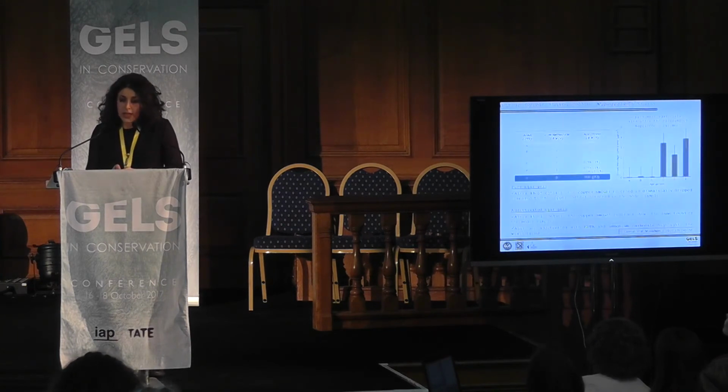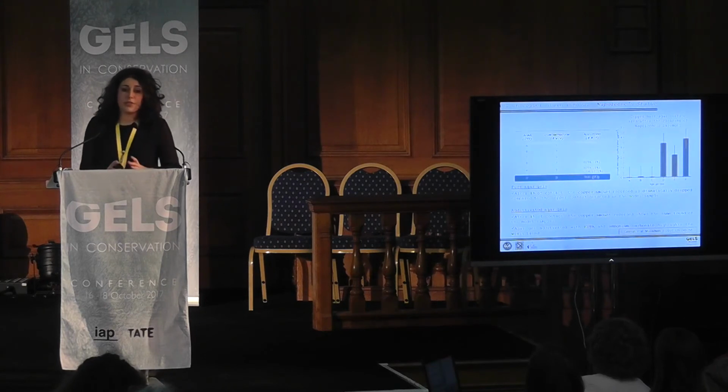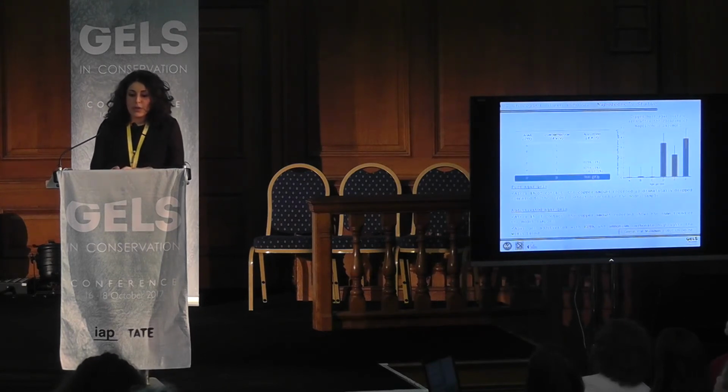In the real case, we have a different trend. For pure agar gels, after 1 hour of contact, the copper amount dramatically drops. On the contrary, for additivated agar gels, the trend is quite similar to that obtained on model samples. In the case of the Napoleon statue, we used the best formulation, the one in which we found the best results, Agar Art at 3% with triammonium citrate.